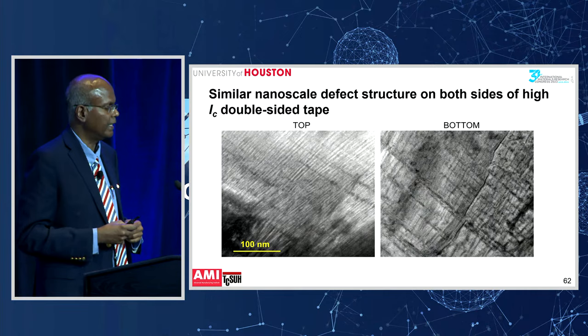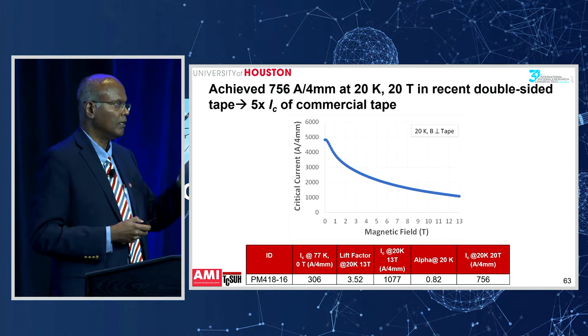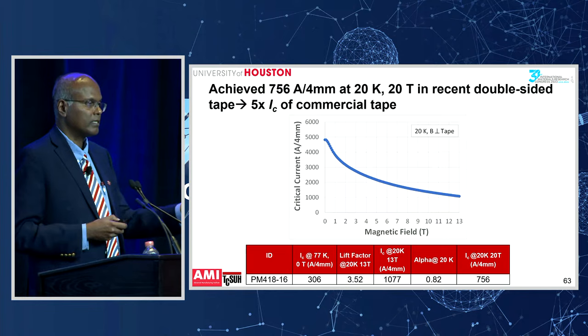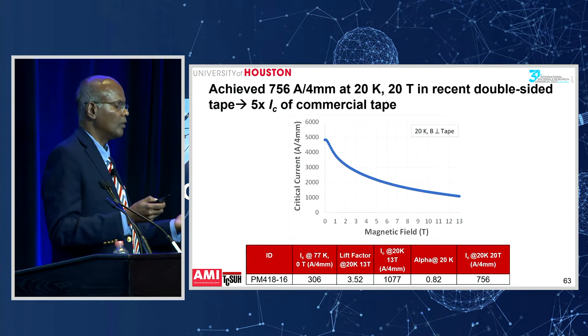So in our results, what you're getting with the double-sided film, even with not very thick films, is 5 times the performance of commercial tape. And our goal, like I said, is to go to 10 times the performance. And with that, this material is going to be a lot more effective than what is available today.